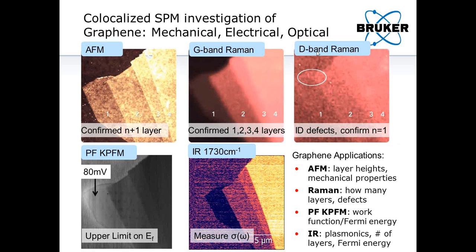We also perform D-band Raman imaging, which gives us a sense of defects, and it also allows us to confirm that we actually have 1 layer. We also performed peak force KPFM on the same region, and from that experiment we're able to extract an estimate or an upper limit for the E Fermi of the single layer region.